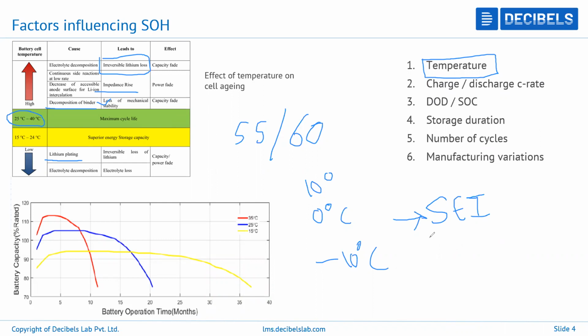So this will form lithium plating. Lithium plating is basically dead lithium ions that stick to the anode. They are dead, which means they are inert. They will no longer react and will no longer participate in any reaction. They won't contribute to the cell's behavior or the electrochemical reactions. They will just act as a hindrance or a block. So lithium dead layers can form, and it is called lithium plating.